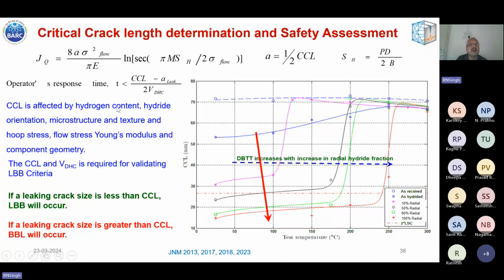So CCL is affected by hydrogen content, hydride orientation, microstructure and texture, and hoop stress, flow stress, Young's modulus, and component geometry. The CCL and DHC velocity are required for validating the LBB criteria. If a leak size crack is less than the CCL, leak before break will occur. However, if a leak size crack is greater than CCL, break before leak will occur, which is not desirable.